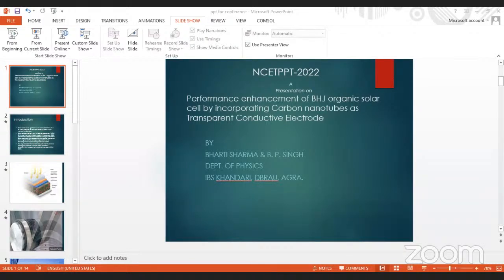Now I'll come to results and discussion. This is our IV curve, which we obtained during the simulation. We can see in the curve that the current increases as we increase the concentration of carbon nanotube. We are getting a fill factor of about 63.14 and PCE around 27%, short circuit current density around 38 milliampere per centimeter square, and open circuit voltage around 0.9371 volt. These are very outstanding results, and they can work in the future.